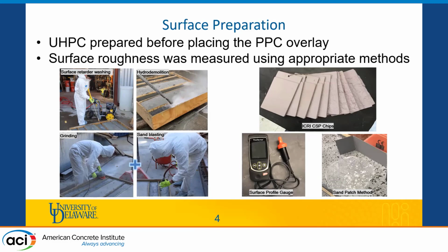For each of these surface preparation methods, we tried to use 3 approaches to quantify the surface profile. The first one is the use of the ICRI CSP chip, which is pretty much a qualitative approach whereby you look at the surface of the chip and you try to mimic what the surface of the UHPC looks like, and based on that, you assign a number to the surface profile. Secondly, we use a surface profile gauge, which is more of a quantitative approach that gives a number to the surface profile of the prepared UHPC slab. And the third approach we used was a sand patch method, whereby you have glass beads that you spread on your UHPC surface, and based on the diameter and the amount of glass beads that goes into the pores, you can estimate the surface roughness.